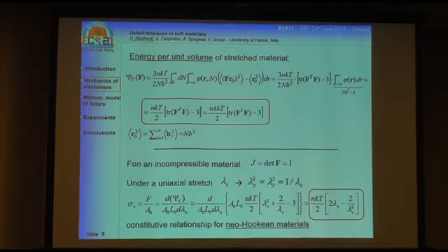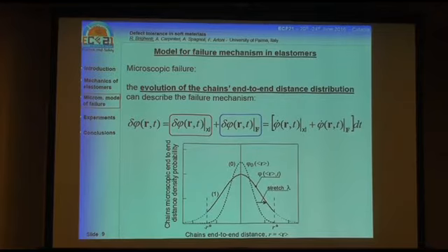If we are considering an incompressible material, as typically occurs for this class of matter, we have, of course, that the determinant of F is equal to 1. And for example, if we consider a single uniaxial stretch, we get the standard stress-strain relation, which is typical for neo-Hookean materials. So we have a nonlinear relationship between the stretch and the stress that we measure in the material. So let's move to the model that can describe how this matter fails under tension, for example.